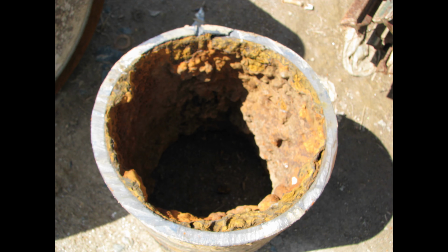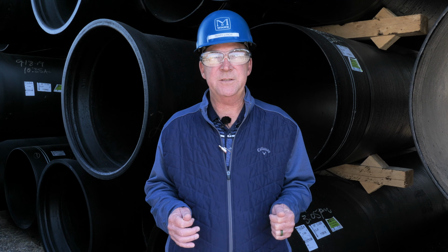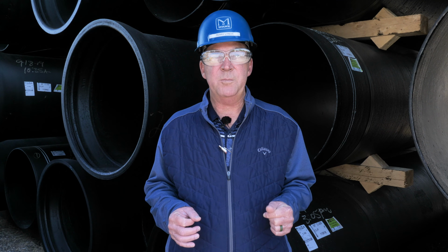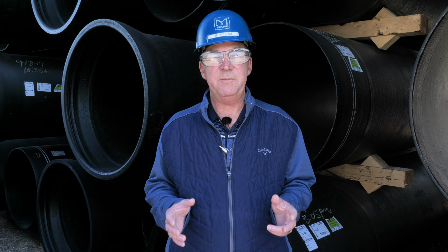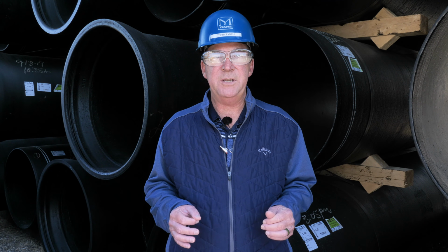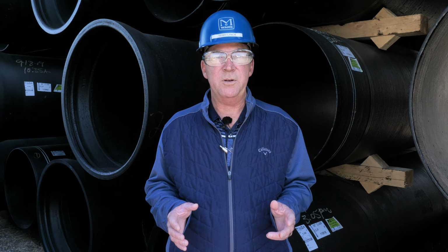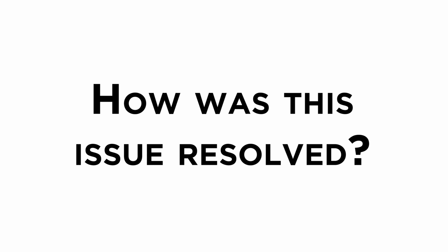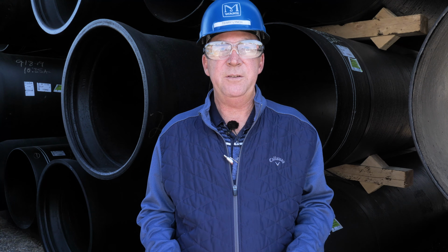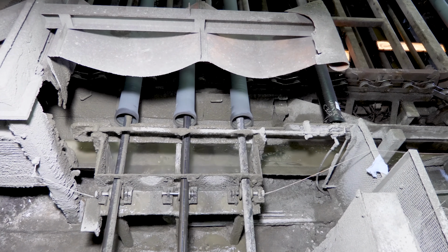pipe. Basically, aggressive water penetrated the pinholes in the bituminous inner surface, and internal corrosion in the form of tuberculation occurred. This led the iron pipe industry to realize that there was a need for a better protective mechanism to combat tuberculation, and thus research and experiments began with cement mortar as the lining material of choice. In 1922, the first cement mortar lined gray iron pipe was installed in Charleston, South Carolina.